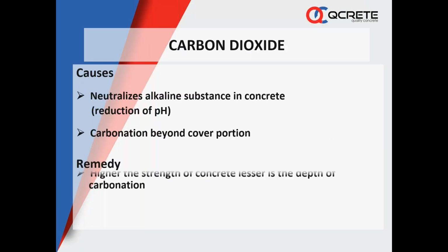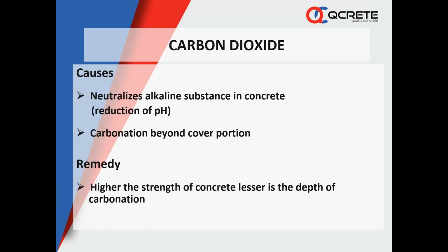Now the third enemy of concrete is carbon dioxide. As I told you earlier, the pH of concrete is around 12 to 13. Over a period of time, what happens? All the concrete which is protruding outside, just like balconies, sees a lot of carbon dioxide, which is increasing day by day. A lot of pollution is increasing in the city. So a carbonic acid forms on the concrete surface, which reduces the pH. It goes beyond the cover portion and the pH comes down to around 8. Then the steel gets exposed and corrosion starts taking place.